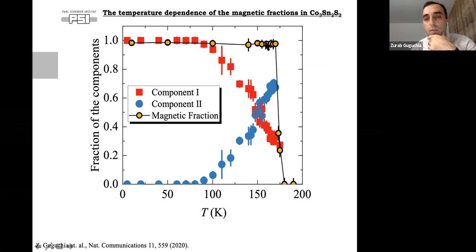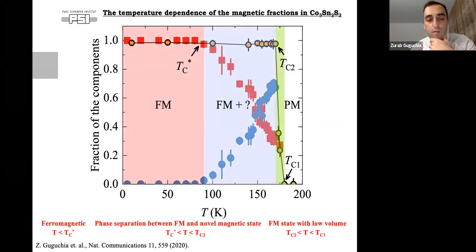And then also it disappears 2-3 Kelvin earlier than this red component. So if I plot the total magnetic fraction, you see that if you just look at the magnetic fraction, there's nothing interesting happening, but clearly you have these two intrinsic components in the system, and you have a large temperature range where these two magnetic components coexist. So I can now distinguish 3 different temperature regimes. One is a ferromagnetic state below this TC star. And then we have a large temperature range where the ferromagnet coexists, or phase separates, with some other novel magnetic state. And then finally it goes into the paramagnetic state. The fact that we have a large temperature range with some phase separation between two states was already a new insight into the system.